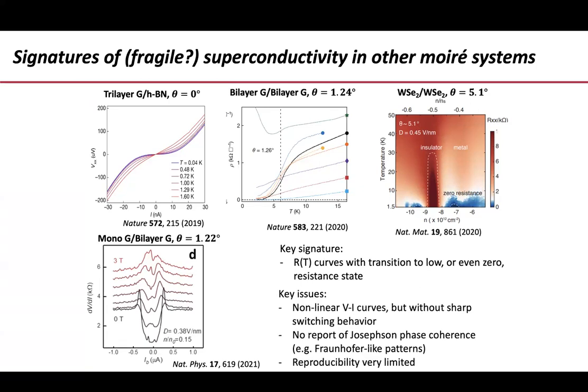However, there were many issues with some of these data. The nonlinear voltage-current characteristics were of this type, not zero dissipation and sharp switching, a clear signature of a critical current, but rather a smooth nonlinear current. And there was no report in any of the systems of Josephson phase coherence. Also, in general, the reproducibility was extremely limited. Samples always looked a little bit weird and so on. Yes, so it's very different.